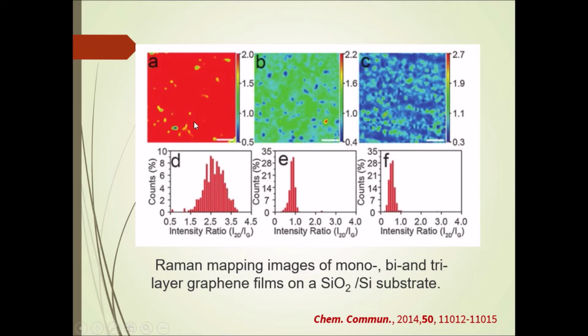Again, we come back to graphene. Also, we can find, in case of graphene, if we have monolayer, bilayer, or 3 layers. We just scan a large area, and by calculating the ratio of the 2D over G mode, we can see if we have homogeneous monolayer, bilayer or trilayer. It is not easy to know if we have monolayer, bilayer, or 3 layers over a large area, a few micrometers by micrometers. We can only know using a high resolution transmission electron microscope. This technique is very difficult and very sophisticated.